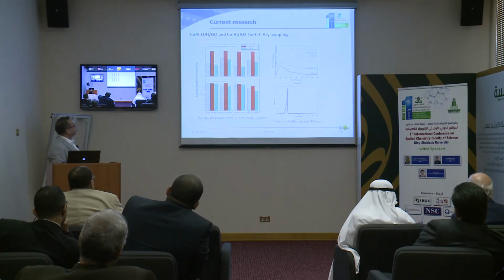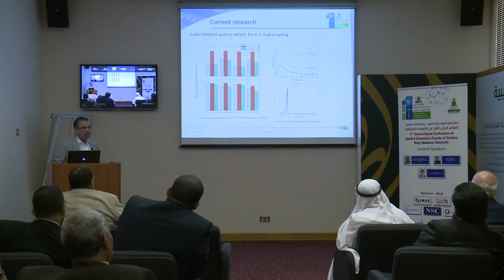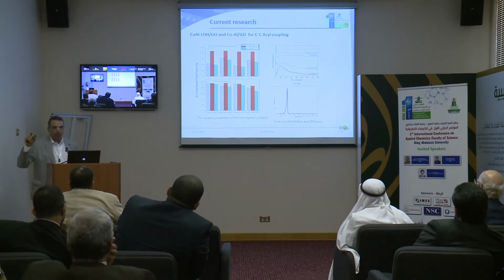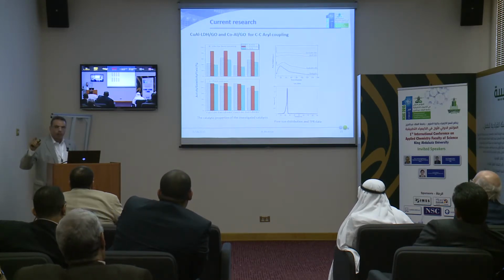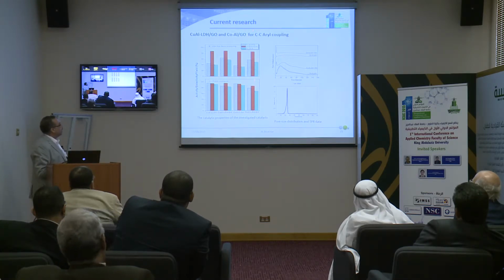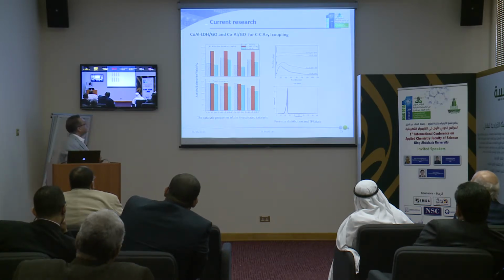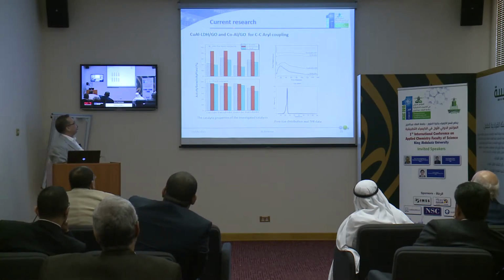under microwave irradiation. Nowadays, our recent work, which is current research, following the beginning of using microwave assisted reaction for synthesis: what if we use layered double hydroxide, cobalt, copper, and so on, without even using the microwave assisted reaction for the synthesis of the CC aryl? In this work, we supported the copper layered double hydroxide on graphene oxide and cobalt aluminum double hydroxide on the graphene oxide, and compared different cations.